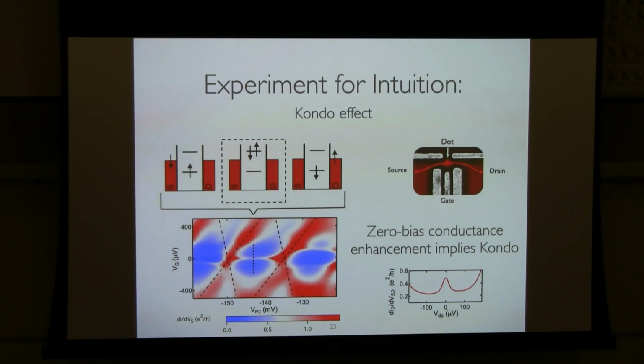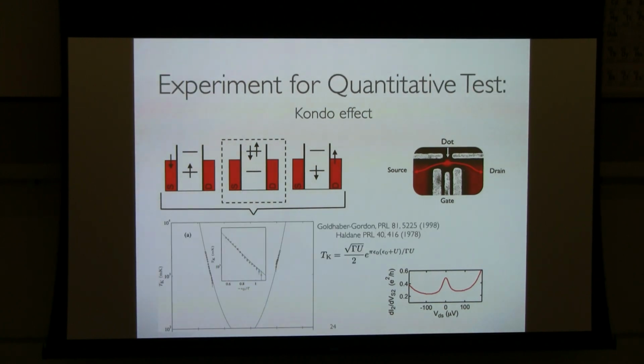But it wasn't yet quantitative, and I decided, all right, let's get greedy and see, can we check whether this works quantitatively? So I mentioned this Kondo temperature, that it's not simply appearing in the Hamiltonian, but it's related. It's supposed to be related based on some simple scaling theory or some crude scaling theory. It's supposed to be related exponentially to the bare parameters of the Hamiltonian, where U is the charging energy, the extra energy to put an extra electron on the system. Gamma is the rate of tunneling in and out, and epsilon 0 is the depth of the level below the